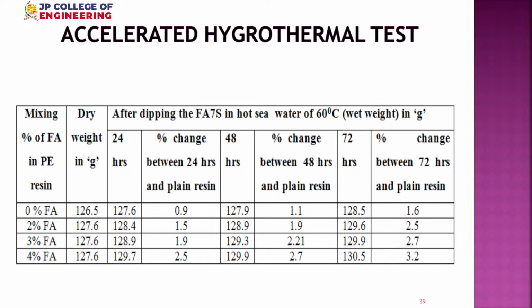Here also one can see that the moment you go for the accelerated test, even the pure resin starts showing some fissuring, and then the moisture absorption takes place. Whereas the increase in water absorption is only marginal in the case of our 2 to 3. At 4% it goes even beyond 3, whereas around 2 to 2.5, these 2 and 3 weight% fly ash is stabilized. 2% water absorption is okay, because pure resin is also going to have around 1.5% moisture absorption after prolonged exposure. So from the accelerated hydrothermal test, we can say our composite with 2 to 3% is suitable for even such applications. Next slide, please.